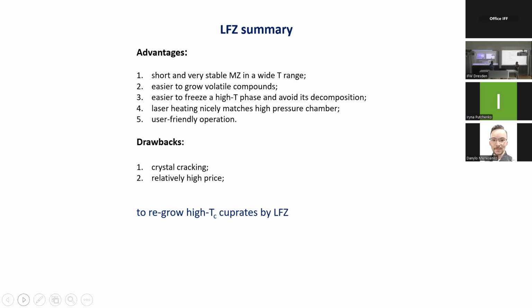So YBCO is higher. But we could pre-melt bismuth-based superconductors. We pre-melt the ceramic feed, so we densify it. We could not apply this for YBCO. It's not a universal approach. Why? It's always correct after pre-melt. So it's difficult to understand why. It's just empirical experience.